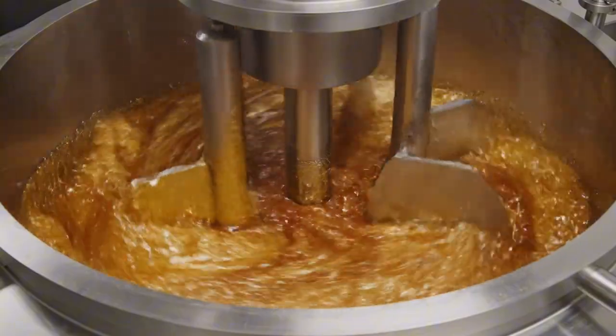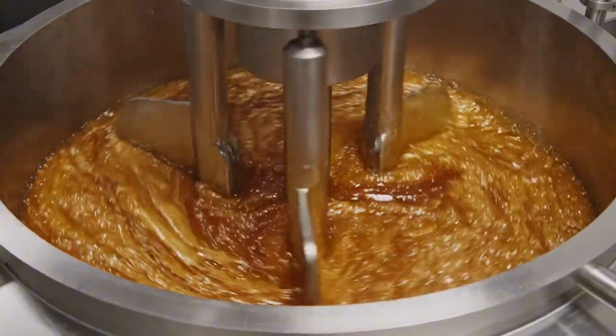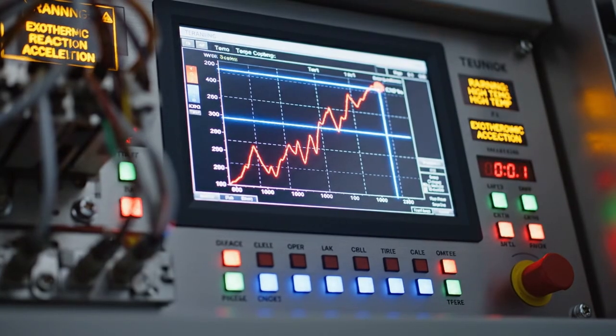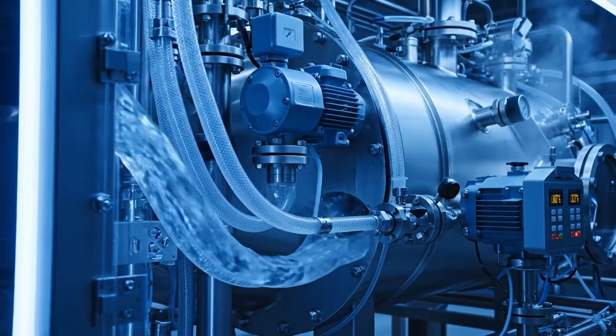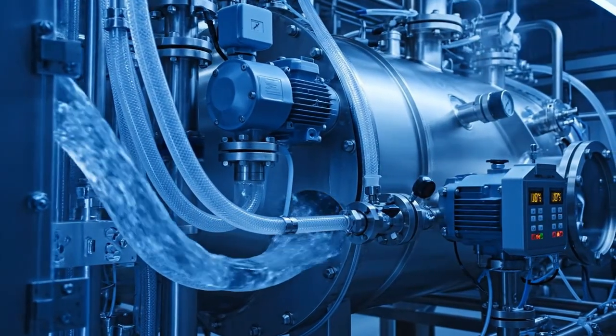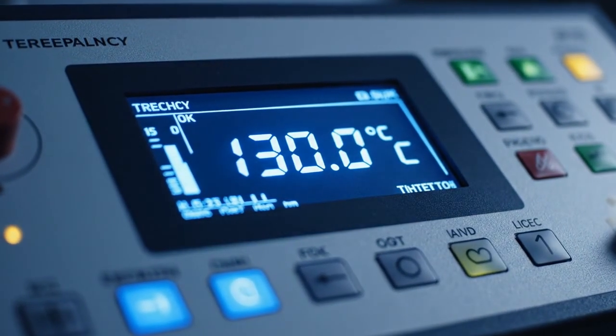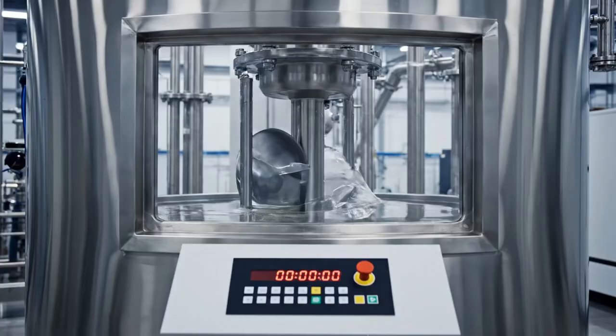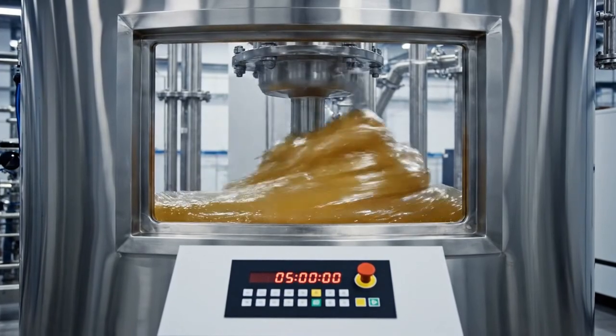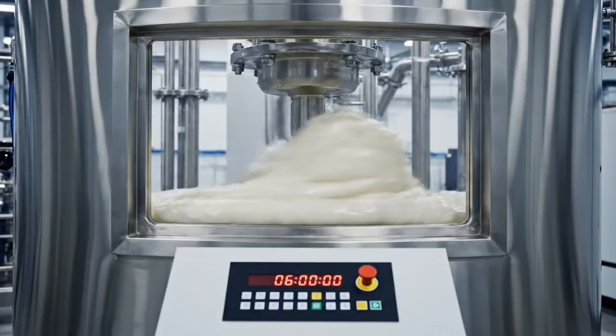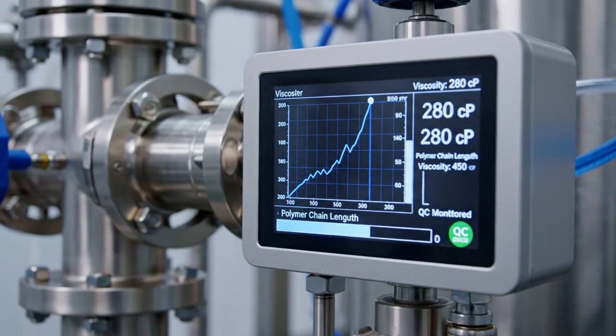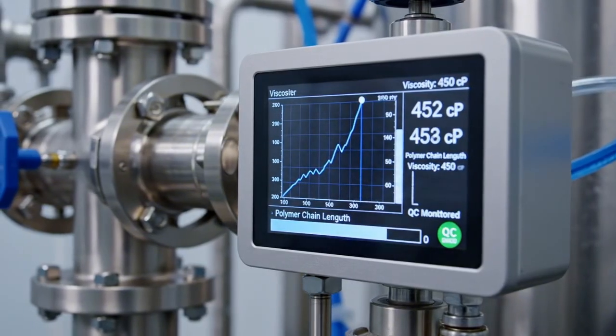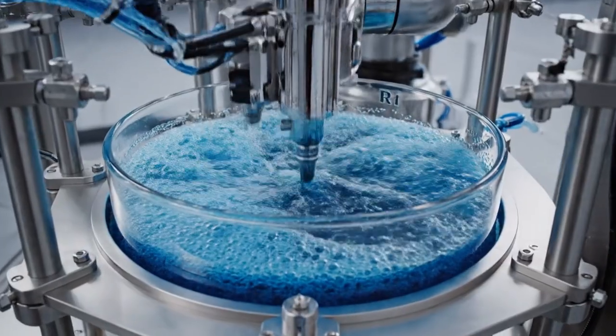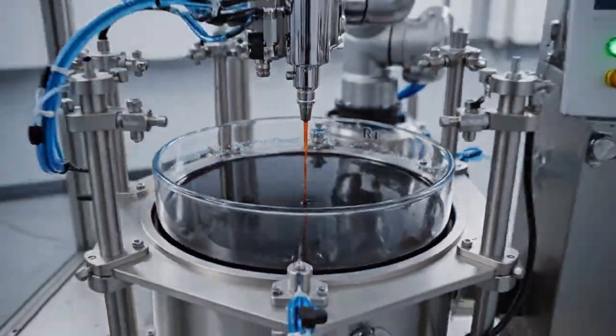Catalysts are added, typically organotin or peroxide initiators, which activate the monomer molecules and allow them to bond with the degraded polymer. The reaction is exothermic, releasing heat that must be carefully controlled to prevent runaway polymerization. Cooling jackets circulate chilled propylene glycol through the reactor walls, maintaining temperature at exactly 130 degrees Celsius. The reaction proceeds for 6 hours, during which the liquid resin gradually thickens as molecular weight increases. Inline viscometers monitor the process in real time, measuring the resin's resistance to flow, a direct indicator of polymer chain length. When the target viscosity is reached, the reaction is quenched with termination agents, and the repolymerized ABS is ready for the final stages of refinement.